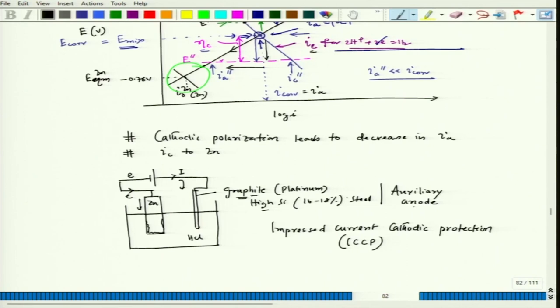So now if we use some metal like, let's say, magnesium, then magnesium would go into serious dissolution, because magnesium is way below zinc in HCl if you compare the galvanic series. So magnesium will dissolve quickly, and finally it will not have any possibility of holding that electrode. That electrode should have a very, very minimal corrosion rate, so that this particular circuit can continue for a long period of time. So the dissolution rate of that particular electrode should be as low as possible, and it only completes the circuit. Okay?